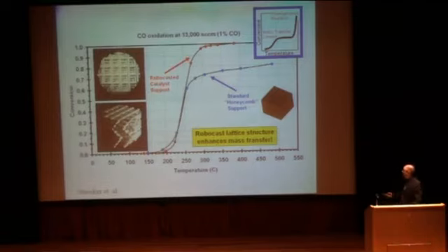And I'll try to quickly show you that this is a comparison between an oxidation reaction where we convert carbon monoxide into carbon dioxide using a platinum catalyst. So a platinum catalyst on this honeycomb structure. You can imagine as the gas is flowing through here, in order for the reaction to occur, that gas has to get to the surface. So it's all diffusion related. However long it takes for that gas to get to the surface, that's going to control the reaction rate.